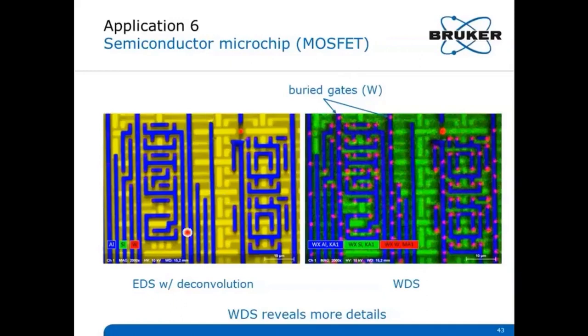The left image is showing the EDS mapping. The right image is showing the WDS mapping acquired at the same time under the same conditions. So you better see where the silicon is distributed. What you also see here is the tungsten. Tungsten indicates buried gates in the MOSFET structure. You can see these gates nicely in the WDS mapping with the red dots here. Tungsten is indicated by the red dots.